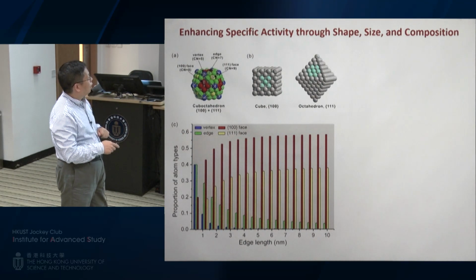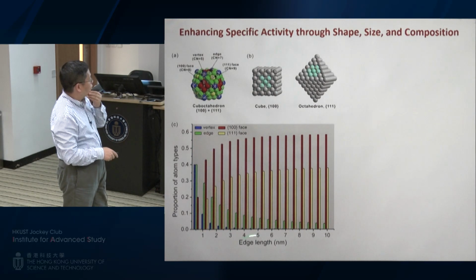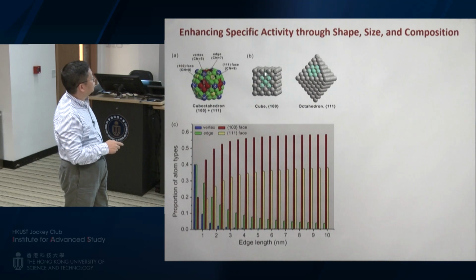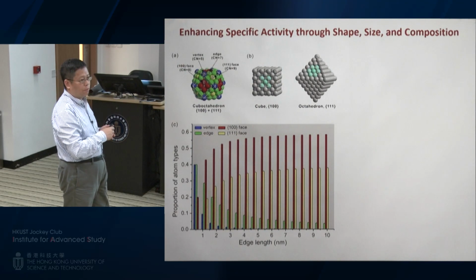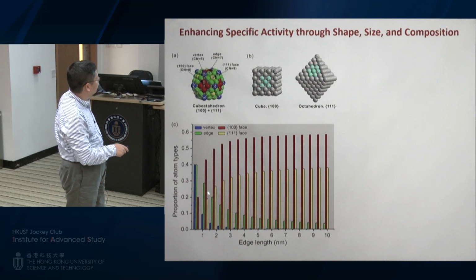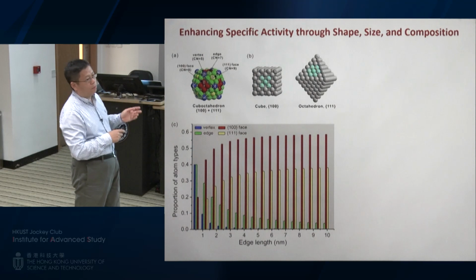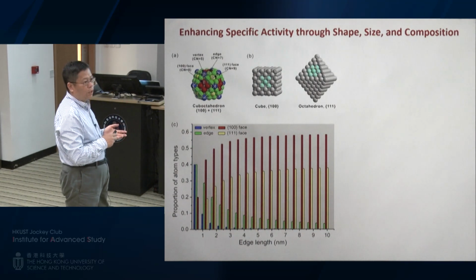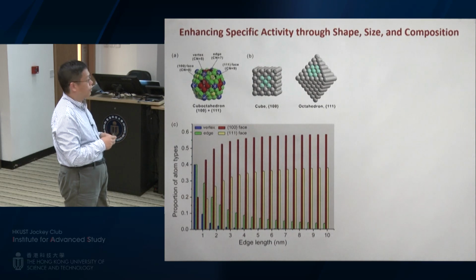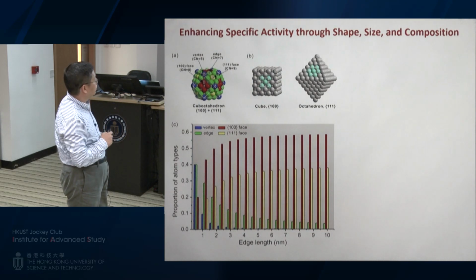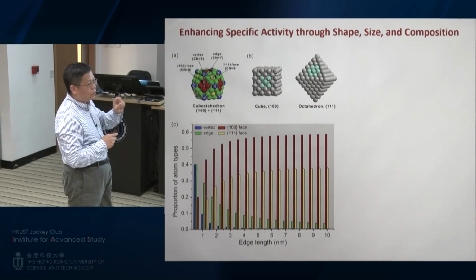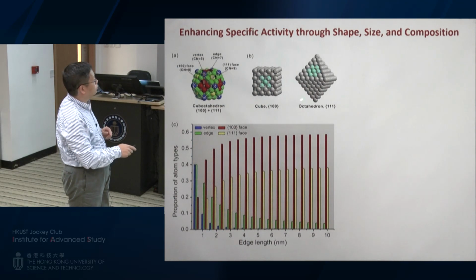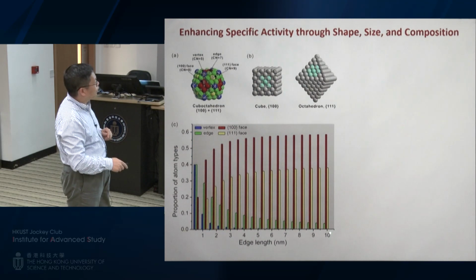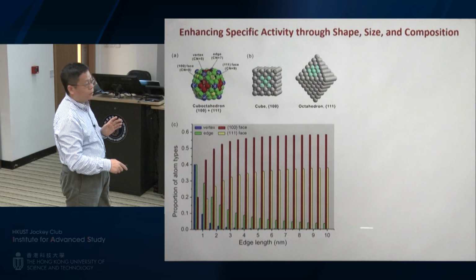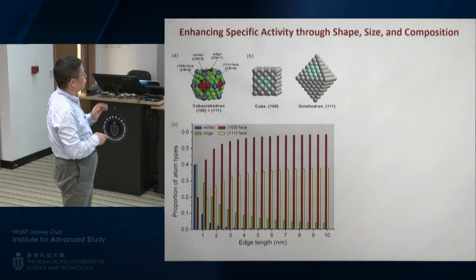However, when you go down to very small size, this is the size of the particle, the proportion of atoms at this specific size is going to be reduced, because the atoms at the corners and edges are going to increase very significantly. So that's why for current commercial catalysts, their size is so small, you won't be able to optimize their specific activity. That's why they tend to give us lousy specific activity. So we have to first increase their size, and then you can take advantage of the surface structure effect. So typically, if you think about surface engineering, you have to think about particles in the range of 10 nanometers or larger, not in this small size range. Okay, so that's about size.